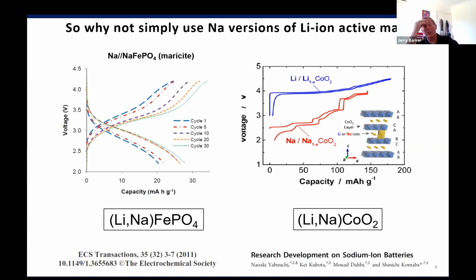Lithium cobalt oxide, well, you can make sodium cobalt oxide. You can make either NaCoO2, which is a structure called O3, or you can make something around Na0.7CoO2. It has a very interesting voltage profile, as you can see in that red line. But the problem with that is it's lower specific capacity to LiCoO2, and the lower voltage means that it's air and moisture sensitive. And clearly what we're trying to do with sodium ion is actually move away from things like cobalt anyway. So that isn't the material that we would possibly use in a commercial cell.